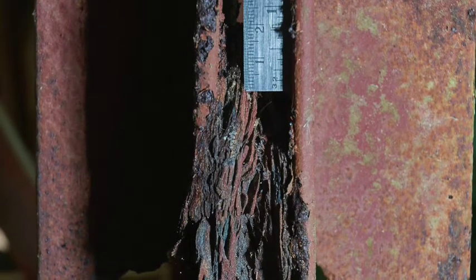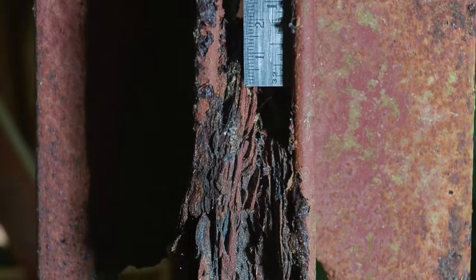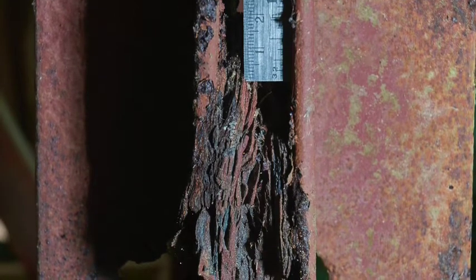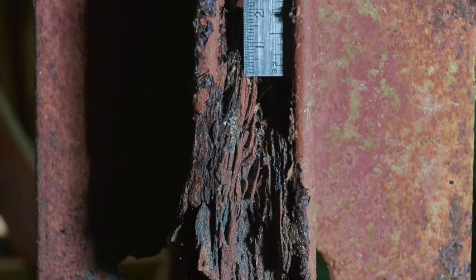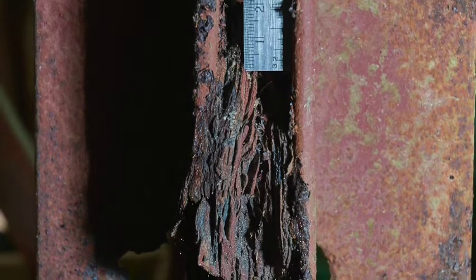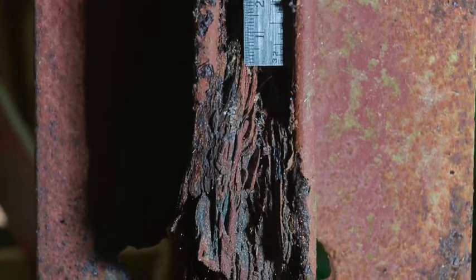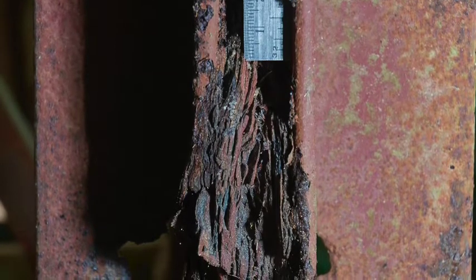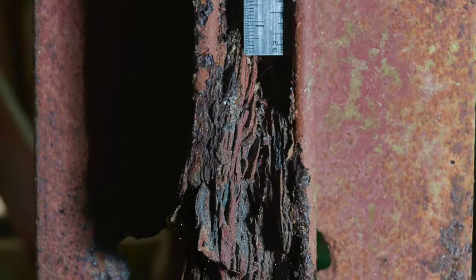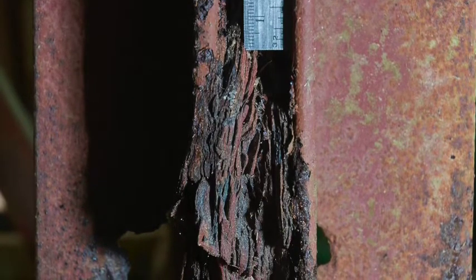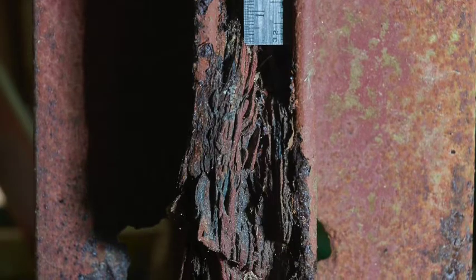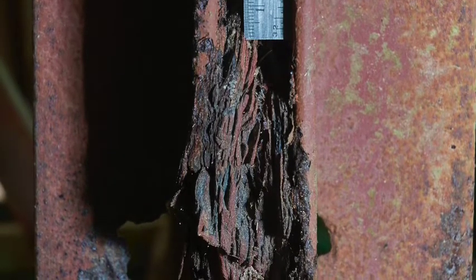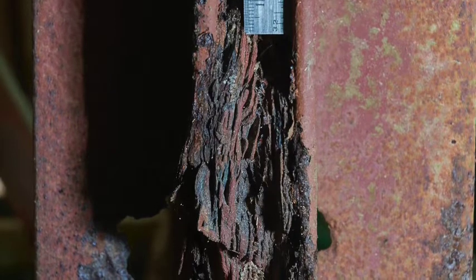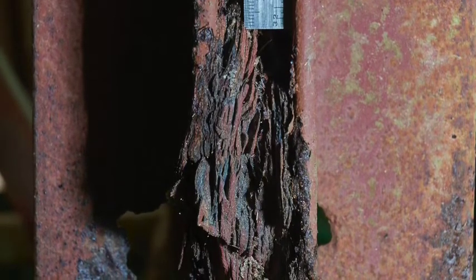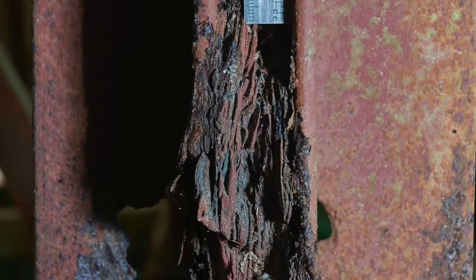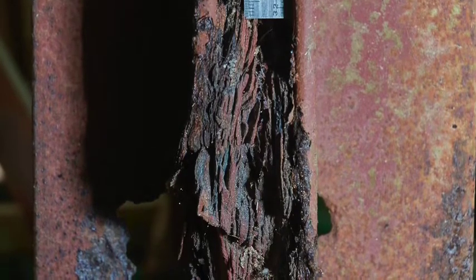And how does that actually physically work, though? So something gets stuck in there and a little bit of corrosion starts. But this looks like there are almost a dozen different individual layers. It's just crevice corrosion manifesting. Yeah. That's how it'll always appear. Okay. It's a very powerful process too, Jack. The corrosion won't stop occurring, so the expansion won't stop either. So not only are you losing steel and therefore structural integrity, the expansion which is being brought about by the corrosion occurring is damaging the structure. It can, for instance, break fasteners and things. If the expansion goes too far, they stretch too far and break.